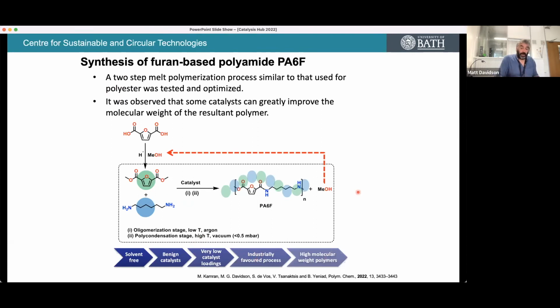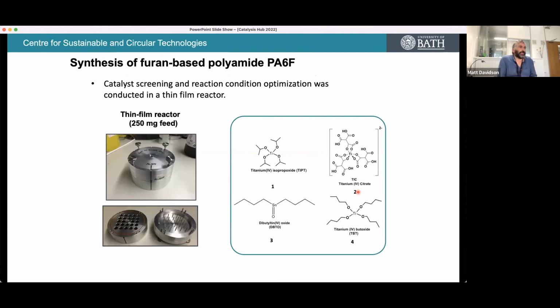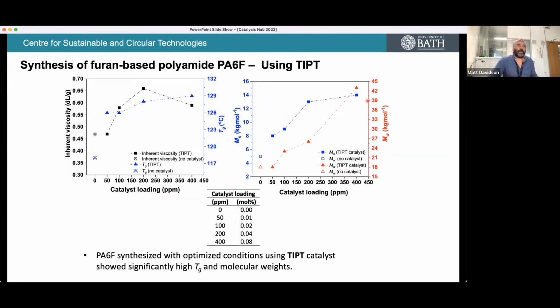And hopefully we can make high molecular weight polymers. Again, just to cut what was actually a very long story short, we were able to screen catalysts using this really useful thin film reactor we have on a small scale. And in screening those catalysts, we were able to make polyamides, semi-aromatic polyamides, PA6F here, where you've got 6 aliphatic carbons and the furanic aromatic portion of the polyamide, up to really good molecular weights here, with good catalytic activity for the